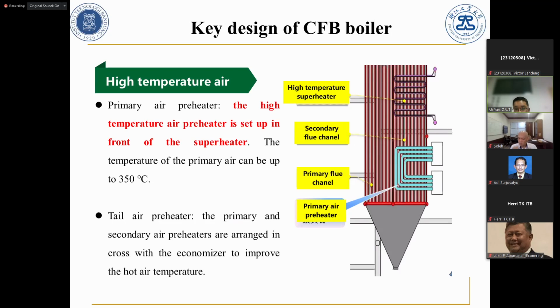And this is how to realize high temperature primary air. So we set the primary air preheater in front of the superheaters, or in front of the low temperature superheaters. So it will ensure the primary air temperature is much higher. The temperature of primary air can be up to 350 centigrade. So it's enough to ensure the combustion is stable.